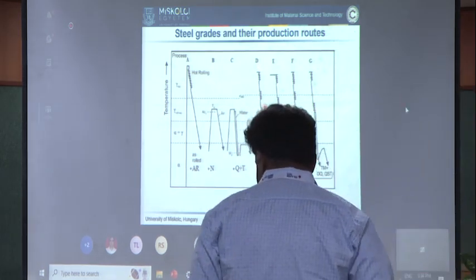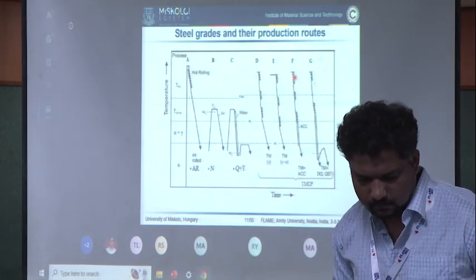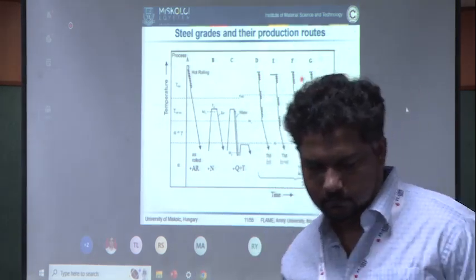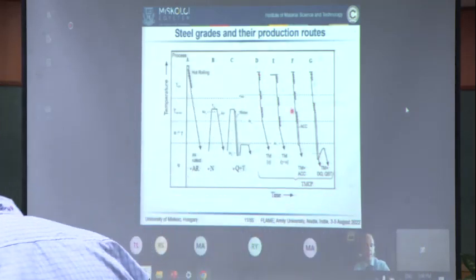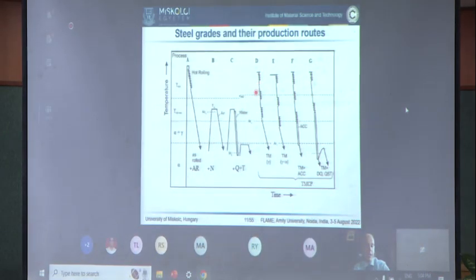Related to the TMCP process, different kinds of processing routes are available. Generally, the process always starts with a kind of hot rolling, but then the rolling process is continued even at much lower temperature, around the A3 temperature, and sometimes even below the A3 temperature. And then very fast cooling is used. Therefore, an extremely low grain size can be achieved with this technology.